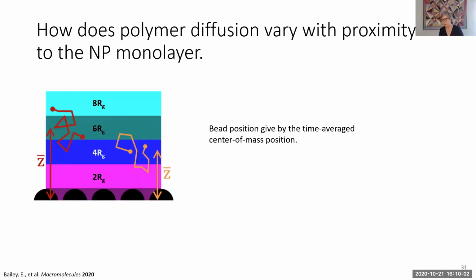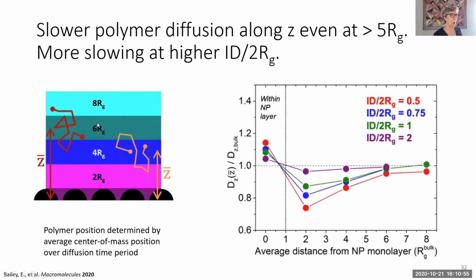Okay, so let's get to the dynamics. So like I said, this is the princess and the pea sort of experiment. And we wanted to know what the center of mass polymer diffusion coefficient was as a function of distance away from the particles. And so we looked at each bead and followed its trajectory, and then calculated its average distance from the particle monolayer. And that's how we binned the data. So we'll have diffusion coefficients where the beads primarily were far away from the particle, or not so far, closer and closer, or even inside the particle monolayer. All right. So that result looks like this.